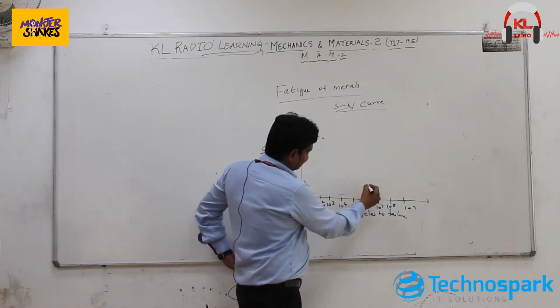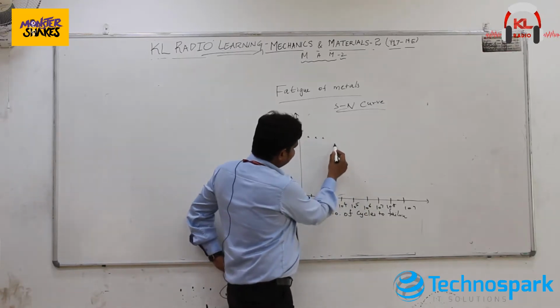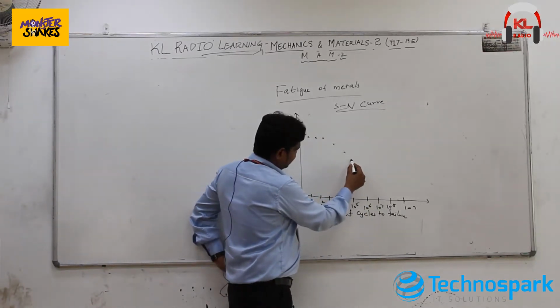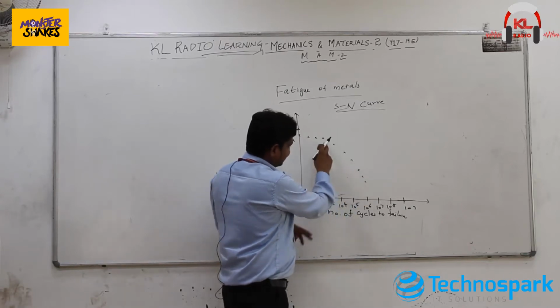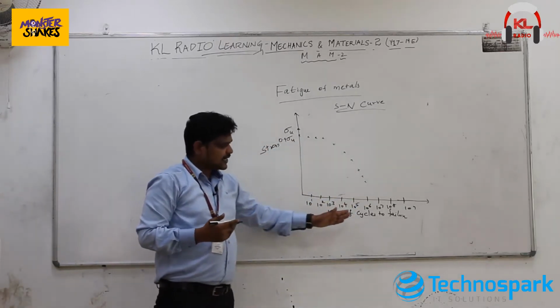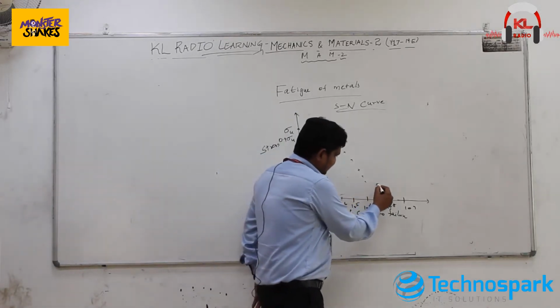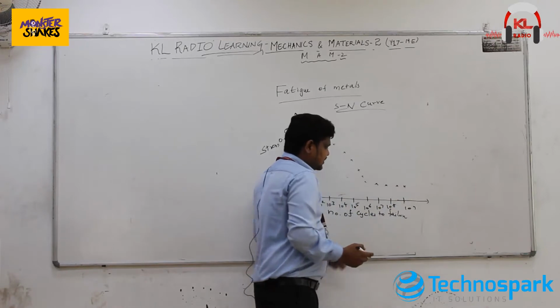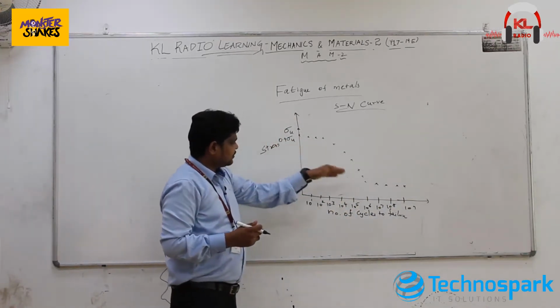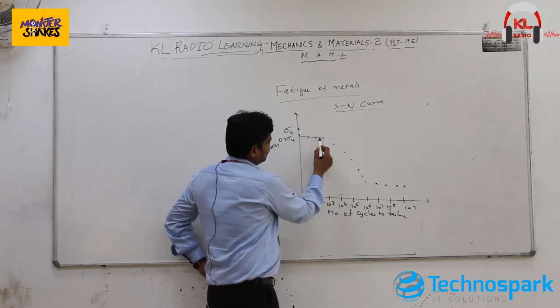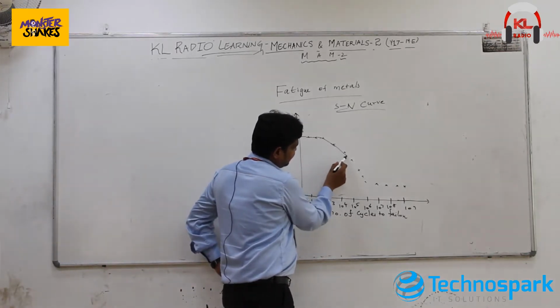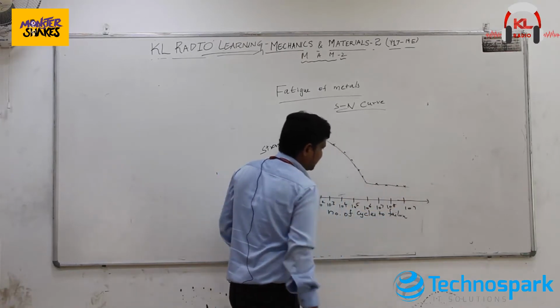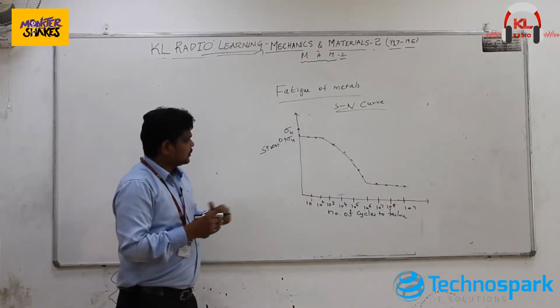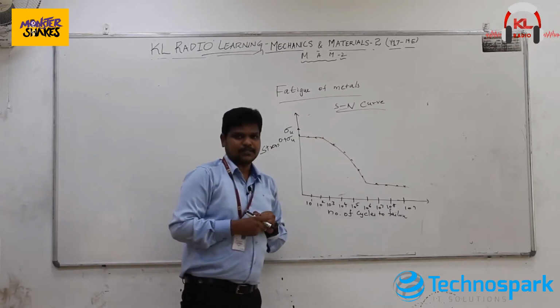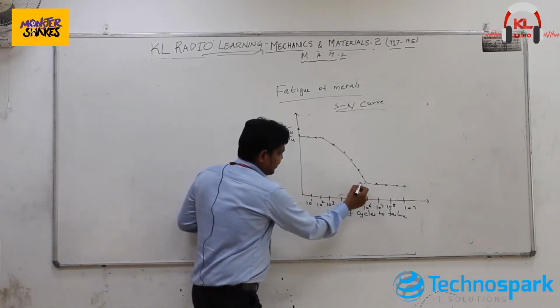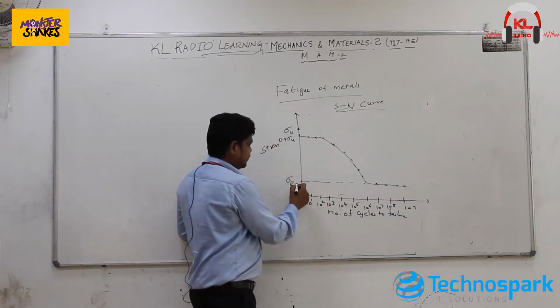After 10 power 3 to 10 power 6, it is noticed that the failure stress with respect to the number of cycles decreases in a linear fashion. After 10 power 6 cycles, there is not much decrease in the stress level for failure. If I draw a line over that, it is just a constant line, and afterwards there is no change in the stress level. So this will be a usual SN curve for certain metals. And here, this point is called the fatigue limit or endurance limit.